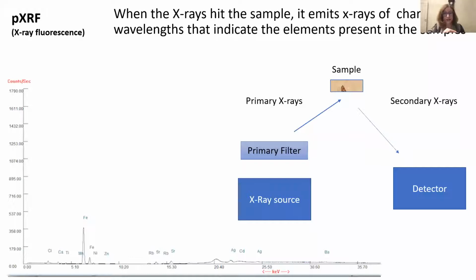The first analysis then we conducted was portable XRF, which is a point and shoot non-destructive technique. And again, I gave you here a bit of a breakdown on what actually is happening. So when the X-ray hits the sample, which is usually performed with a portable XRF gun, it emits an X-ray characteristic wavelength, which is then received by the detector. It indicates, like in the spectra presented in the slide, the elements present in the sample at that specific point.